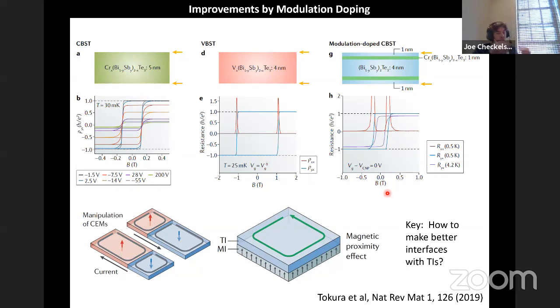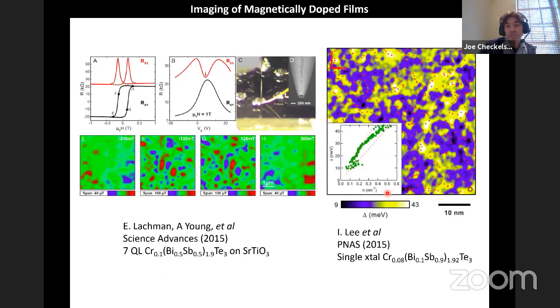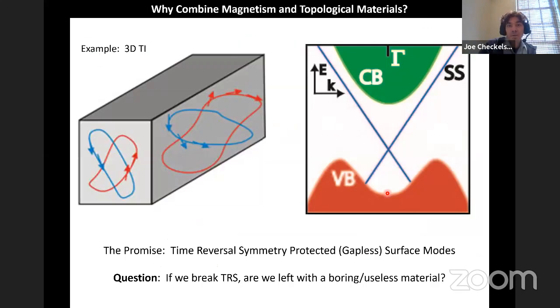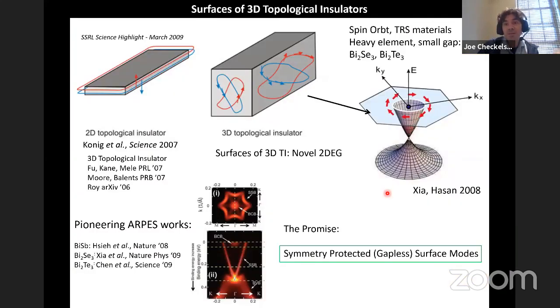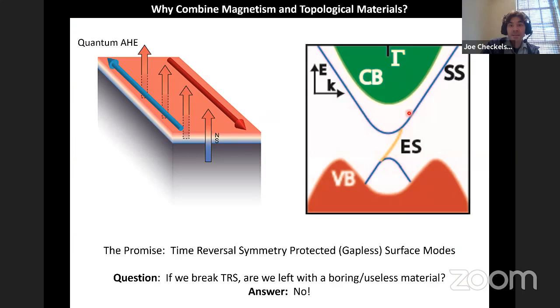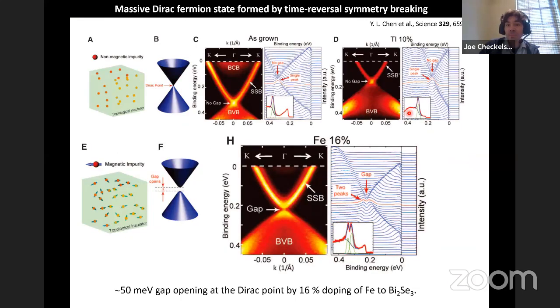So it's very important to be able to distinguish between conventional surface modes and topological surface modes, and there are different ways of doing it. One spectroscopic way is that, for example, in topological insulators, if I go back a little bit, and I didn't mention this, so I'm glad it was asked, you do expect a particular kind of winding of the electron spin degree of freedom, which in principle should help you distinguish these surface states from others.